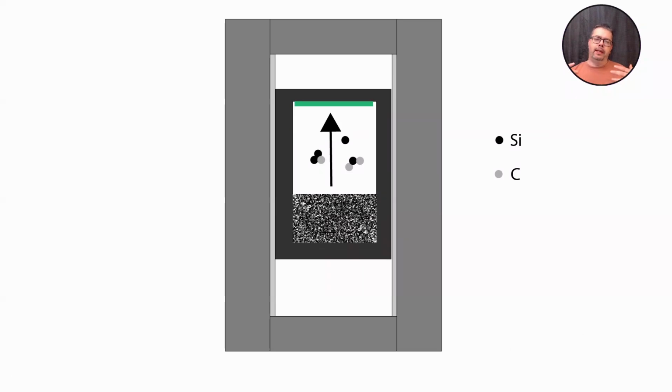And the principle is that you have a source of silicon carbide, powder or a ceramic, and then when you heat it up, you have the vapor species which are formed: Si2C, SiC2, Si, and other ones. And then those are transported from the source to the growing substrate. And this is what is typically done in the traditional PVT. And this is a very simplified illustration now.